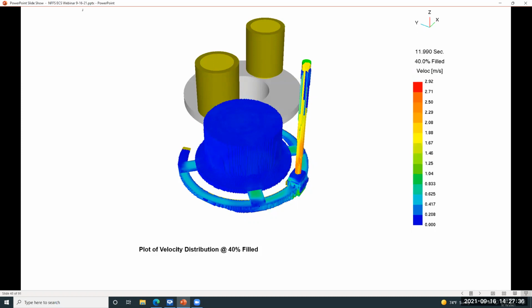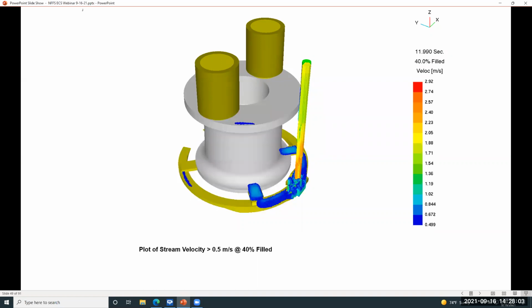We're looking at getting flow of metal in as calmly as possible, especially in the non-ferrous alloys, because they tend to be prone to dross formation and getting oxide mixed up. So we're looking here, we're getting nice, slow metal velocities. So our lower values, the dark and medium blues. And in this case, we were doing a plot of anywhere where the metal was going faster than 0.5 meters per second. And this is sort of a typical cutoff value. We would like to keep the metal velocities below that, and we can see that we're doing that quite well here. The only area where it's going faster than that is the initial metal down into the sprue.